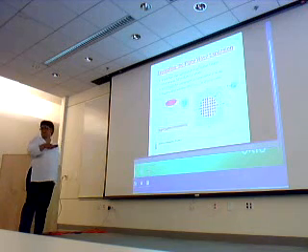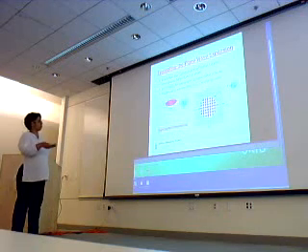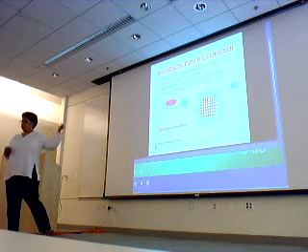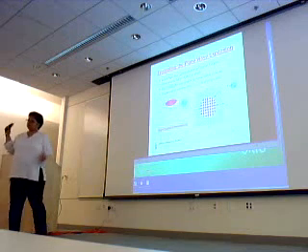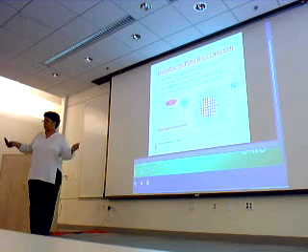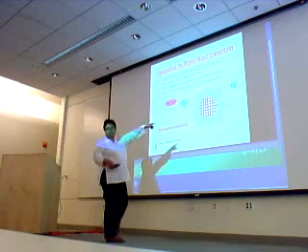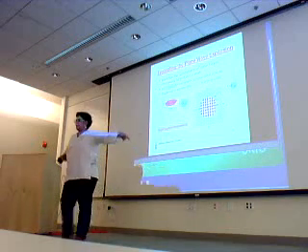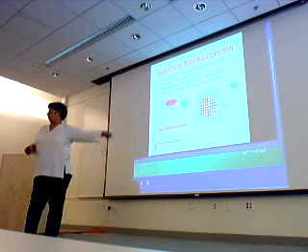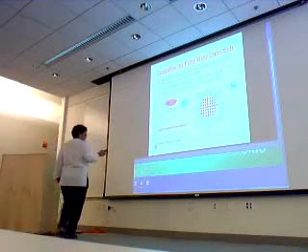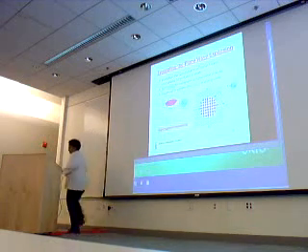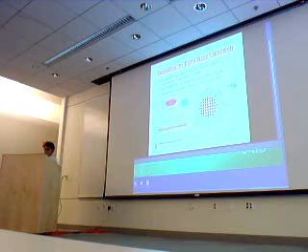So this is an equation of a sphere. Okay? And so what you do is you draw such a sphere in reciprocal space, and then you keep all the k plus G's that fall inside this sphere. Okay? And now comes the point that I mentioned before, which is if you have a very large unit cell in real space, then you'll have a very dense mesh of these magenta points in reciprocal space, and so you will have a lot of plane waves falling inside your cutoff, which will make your calculation more expensive. And there's an input parameter that you have to give your PWscf code, which tells you what that plane wave cutoff is.